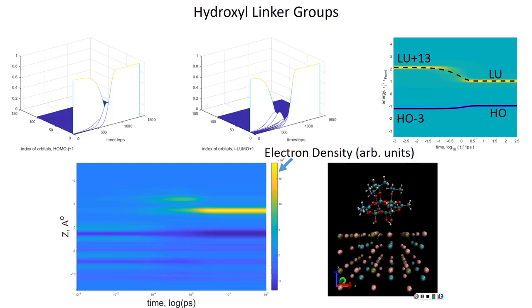They synthesize these small polyoxotitanate clusters, place them into a type of organic matrix, which holds them separately, and then they take XRD data of those clusters themselves, and you can find that on different databases. So you're telling they're chemically stable? Yes, more or less, yes.